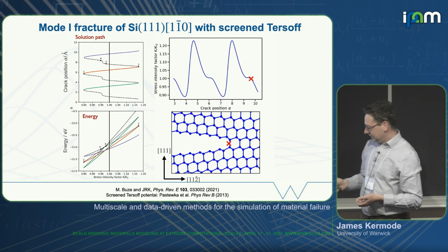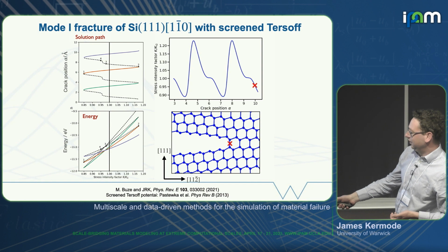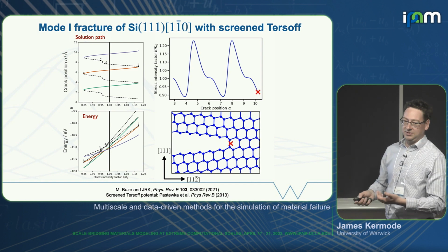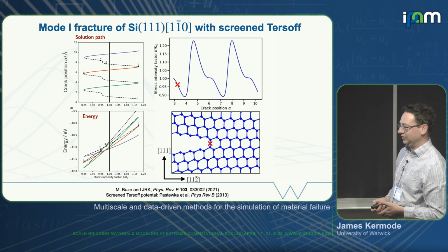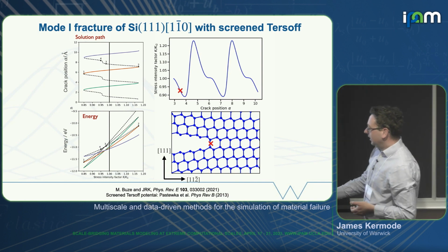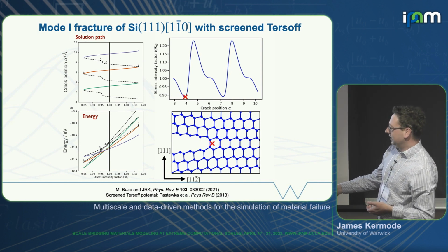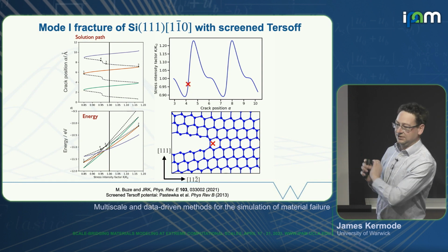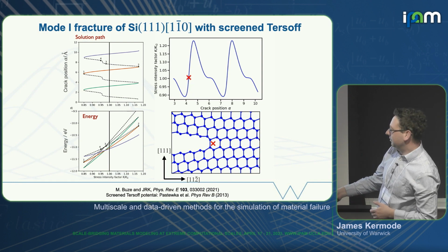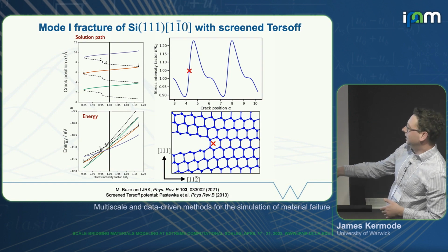That's the Griffith load. It doesn't exactly match the estimate of the Griffith load that we would get from the elastic constants, probably because of finite size effects in this case. That's something to investigate a little bit more. If we go to the right of that, it's favorable to advance, so purple is below green. If we go to the left, it's favorable to heal, for the crack to go backwards, so purple is above green in this landscape.